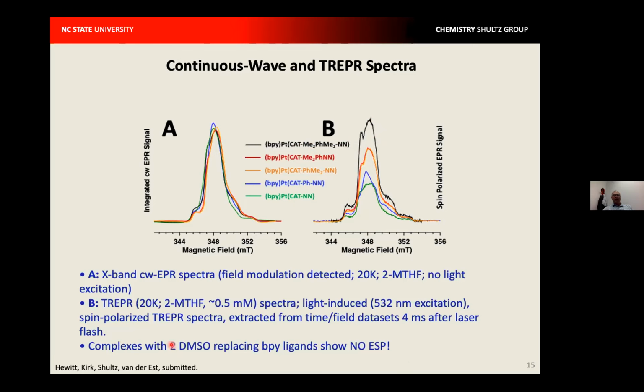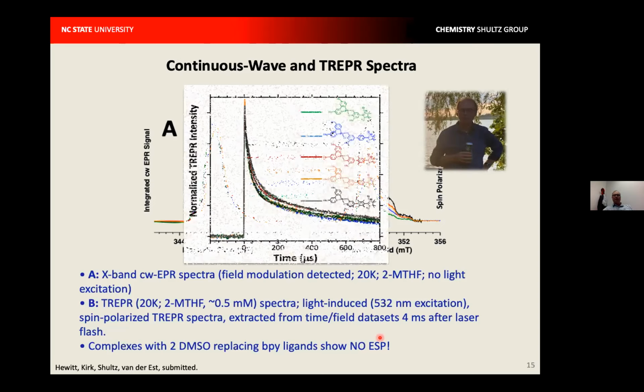Importantly, if we take a look at the complex with DMSOs replacing the diimines, we get no ESP whatsoever. So we need this chromophore-radical coupling to generate ESP that gives us enhanced absorptive ESP by the reversed quartet mechanism. And so these experiments were done by Art van der Est at Brock University, who's been a great collaborator. I'd like to point out that while the spin polarization is generated in under a nanosecond, the EPR signal lives for over a millisecond.